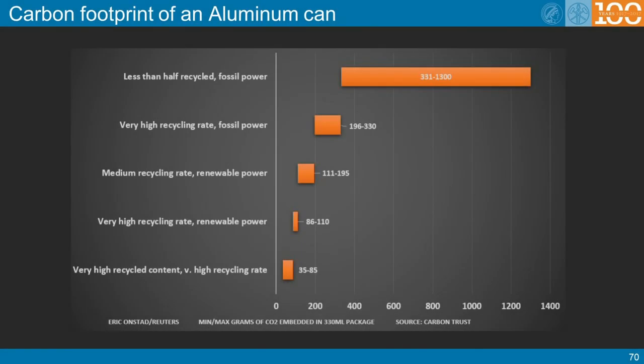This comparison analyzes the carbon footprint of an aluminium drinking can. The color bar gives the carbon footprint in grams of CO2, embodied in a 330 milliliters sized can. The range between minimum and maximum depends on the specific origin of the fossil fuels that were used during production. An aluminium can that uses less than 50% of recycled material, and correspondingly more than 50% of primary aluminium, produced by using fossil fuels for electrolysis, has indeed a very high carbon footprint.